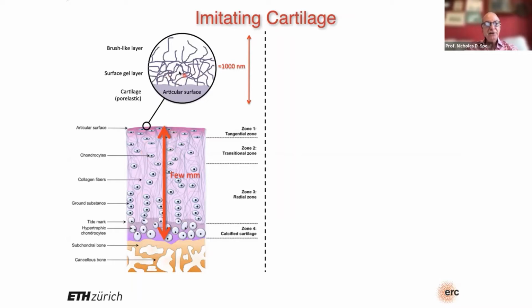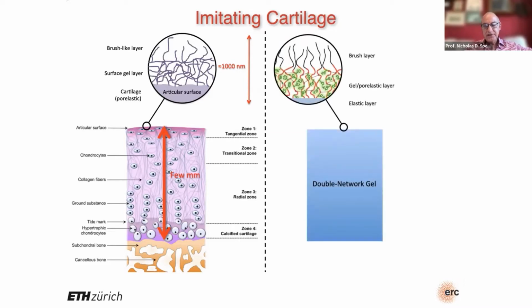On the top of it is a surface gel layer, very soft, and on top of that is an even softer layer of dangling chain ends, mostly polysaccharides. And this plays a major role in the way in which the cartilage lubricates. And our idea was to try and use polymers to achieve a similar effect, partly to understand more about cartilage and partly to be able to develop new materials based on the principles of cartilage. And we also wanted to use a brush layer, but a polymer brush layer, some kind of gel layer, and maybe using a double network gel to imitate the underlying solid cartilage.